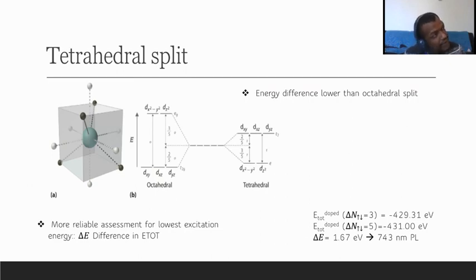the three electrons that would be at higher energy than the two of them that were supposed to be at higher energy in the octahedral split. But here the energies are not as high as the octahedral one, because as the lobes are closer to where the point charges are, there will be higher energies coming from the Coulombic interactions. And